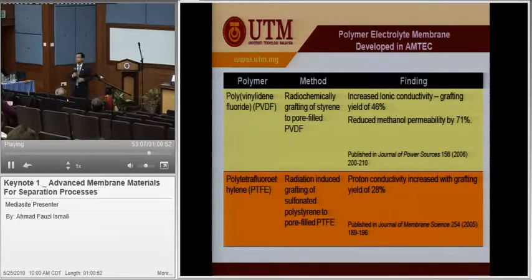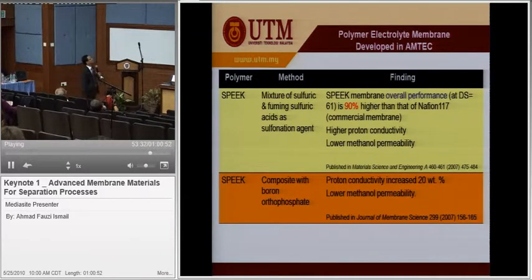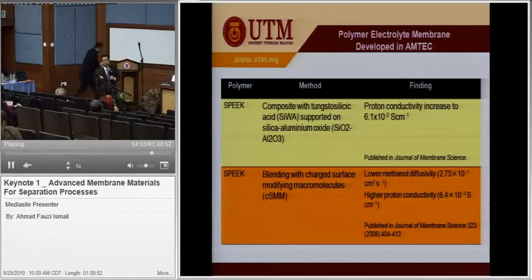So this attracted Nissan Motor from Japan to come and discuss with us. Again, we developed that for PTFE, and the yield increased about 28%, not much, but we managed to publish it. It was very early research, way back in 2005. Again, we kept improving the material, and in 2007 we developed SPEEK, sulfonated polyether ether ketone, and we managed to produce 90% higher proton conductivity than the commercially available Nafion. Again, we developed SPEEK, tested it again, and the latest we developed SPEEK in cooperation with titanium oxide.